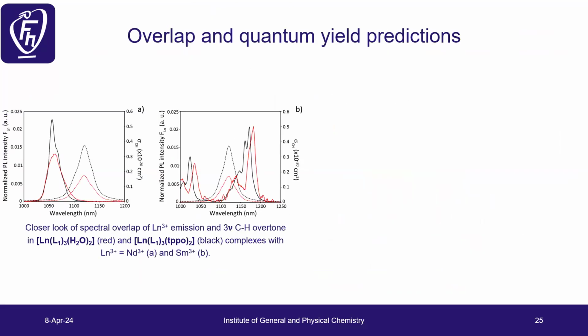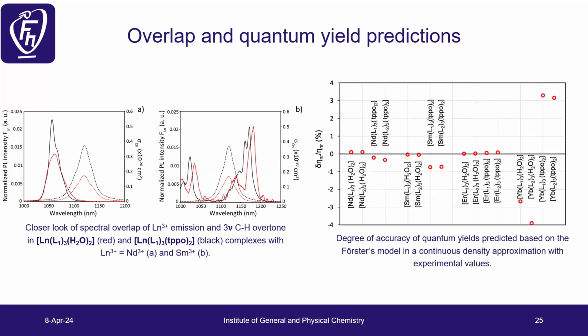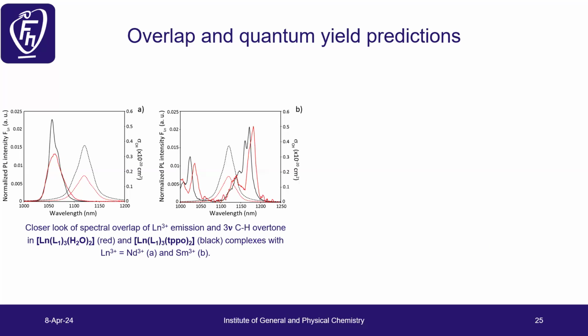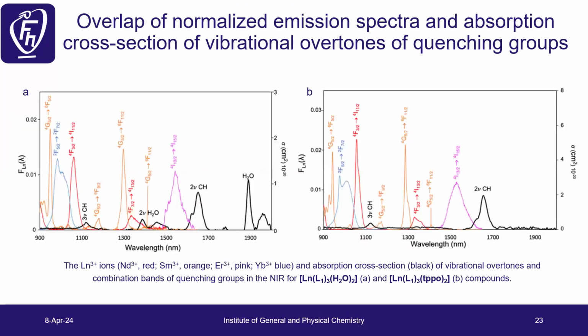Also here we can see closely how the overlap of neodymium and samarium looks with the second and third harmonic of CH groups. And here we made a prediction of the accuracy of our quantum yields, where we obtained quite good results, except for ytterbium, because there exists a third harmonic of OH here, but it's quite broad and we cannot see it on diffuse surfaces when we measure it.